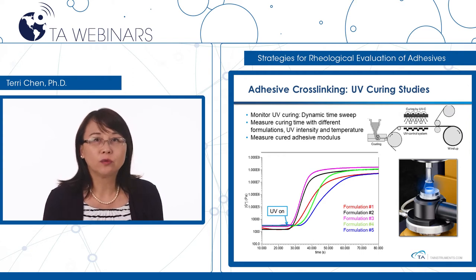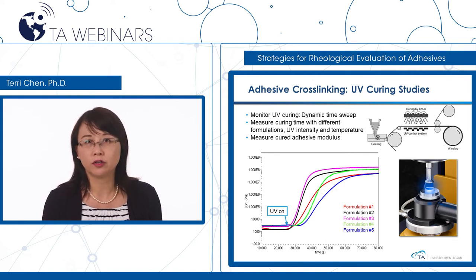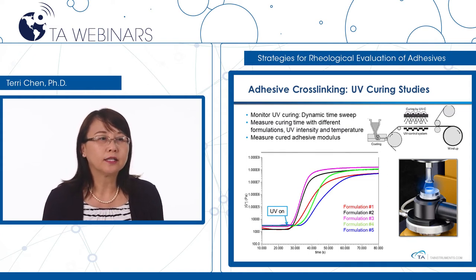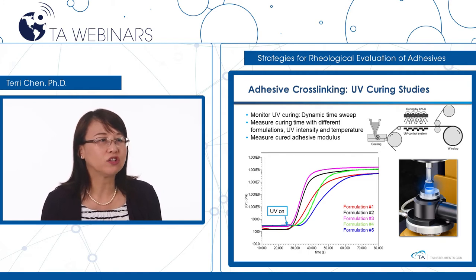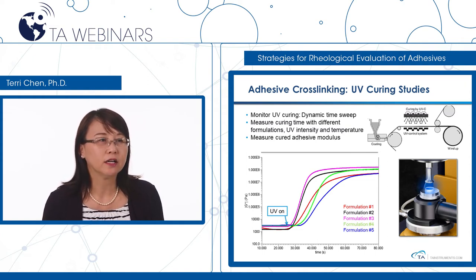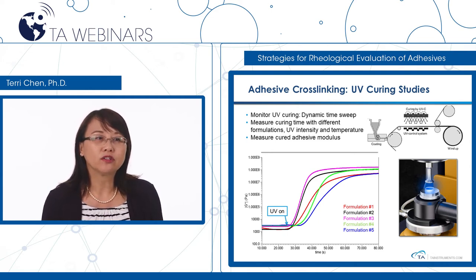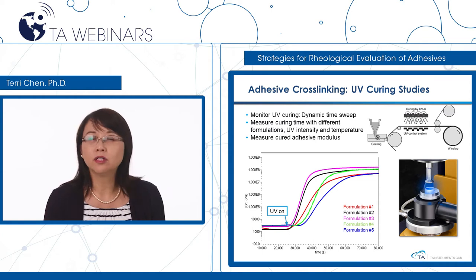Many adhesives are cured through heat, UV radiation, or under humidity. A dynamic time sweep experiment is typically used to monitor curing. This figure shows an example using a UV curing accessory attached to a DHR rheometer. The UV light with controlled intensity was triggered on after 25 seconds of equilibration and remained on for 30 seconds. During this time, the modulus change of five different formulations was monitored. This type of rheological test allows quantitative measurement of adhesive curing with different formulations, different controlled UV intensity, and also at different temperatures.